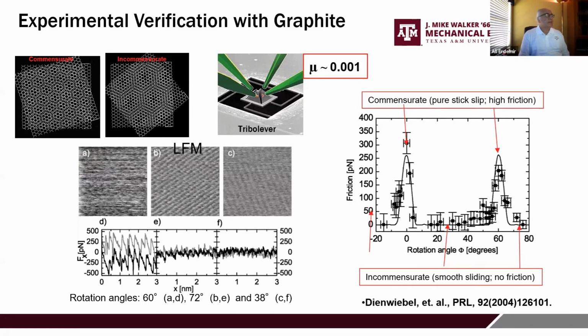And they used this nanoscale tribometer, which they call a tribolever, and they attached a layer of graphite or graphene to the surface of the tip, and rubbed this against, on the bottom, another highly oriented pyrolytic graphite. So by twisting these two surfaces, these two pieces of graphite, on the other side and also on the surface, they were able to see the situation where you would actually have very huge stick slip or adhesive interaction. By twisting it slowly, they were able to show that, after reaching a certain twist angle, friction would nearly vanish.